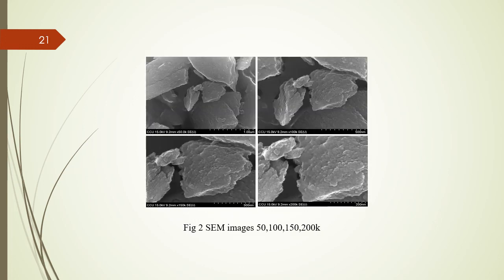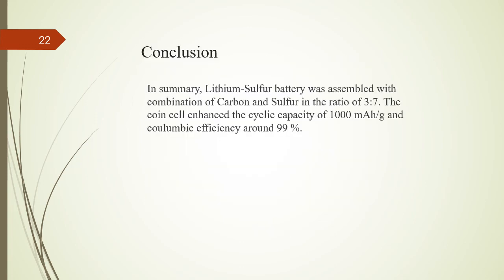So here are the SEM images at 50, 100. This is 50, and this is magnification at 100K, and this is 150K and 200K. So far the surface of the carbon and sulfur material, which is the active material, is uniformly mixed, and it is very smooth judging by this morphology from the SEM image. So finally I have assembled the lithium sulfur battery and achieved 1000 mAh per gram